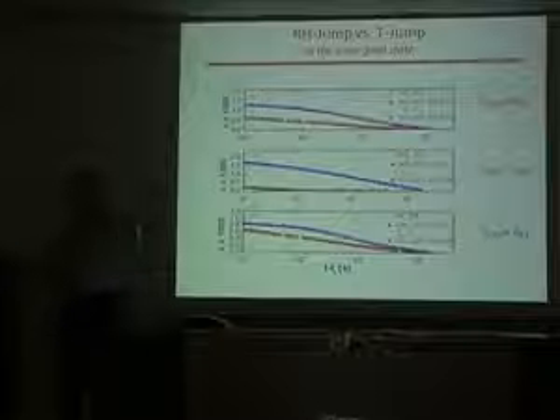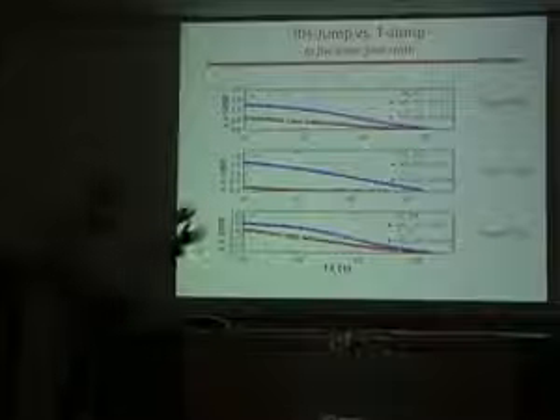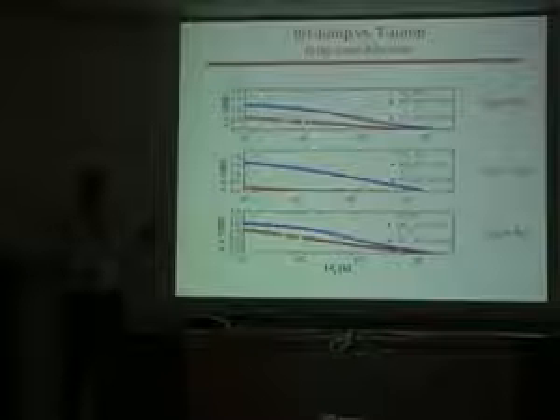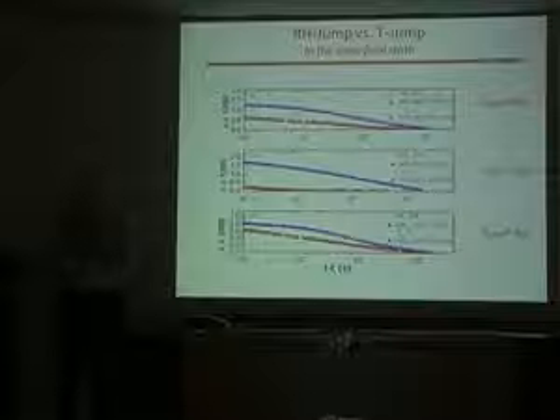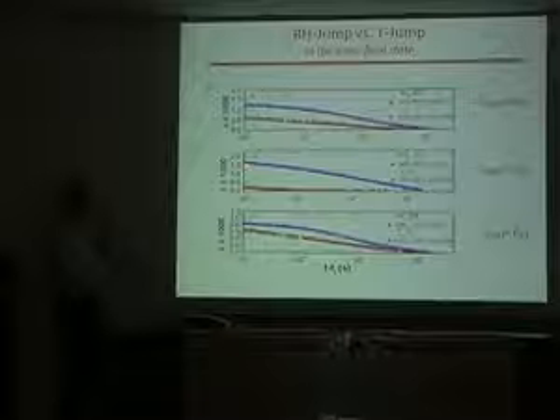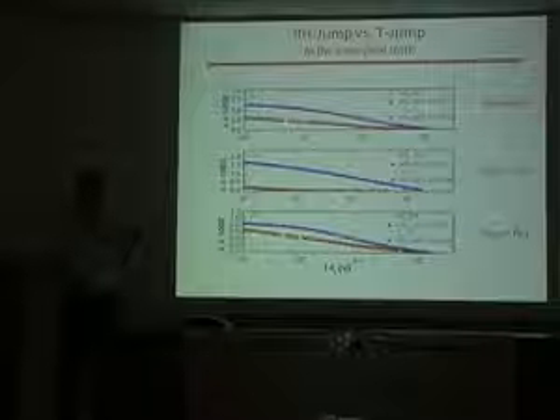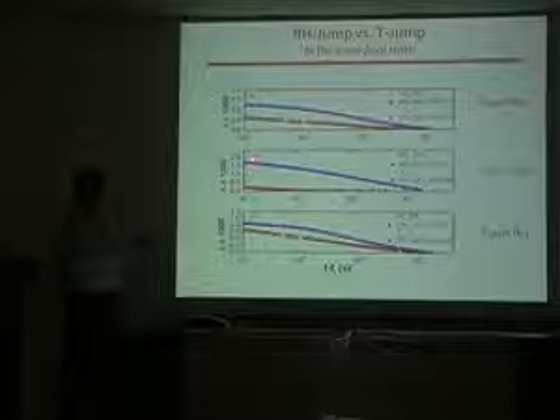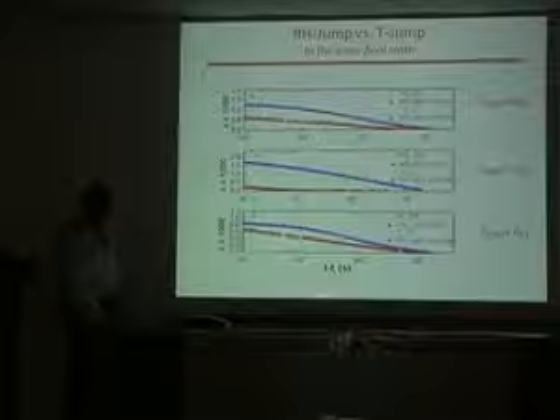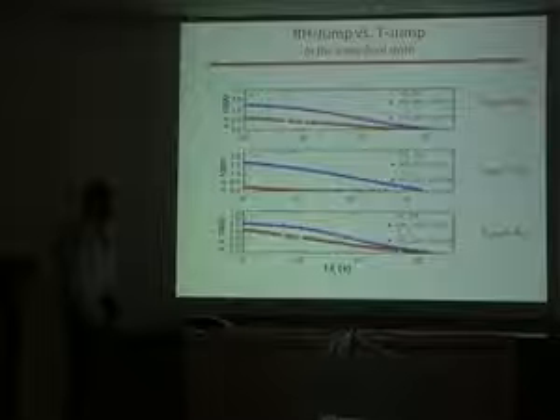So that was the first hint that maybe there's something different about the humidity-created glass compared to the temperature-created glass. So I said, we know it's path-dependent. We didn't know that this would lead to it. It also is, in any simple fashion, quite contrary to the ideas of free volume, because here I have a higher free volume, and yet it's relaxing more slowly. Okay? So that's actually a difficulty for free volume models. I expect it's probably a difficulty for enthalpy models too.